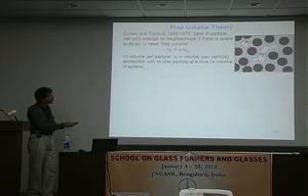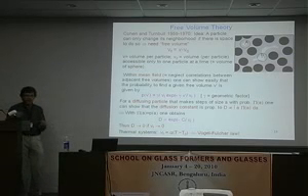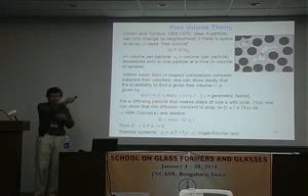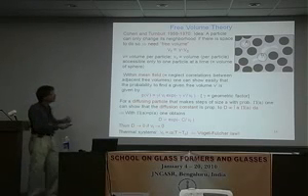And so what you introduce is the so-called free volume, which is the volume which is accessible to the particle. That is to say, the white volume here. It's the sum over all the white volumes divided by the number of particles in order to get an intensive quantity. So that's your V_F. Now, you are making a mean field approximation. That is to say, you are not looking whether or not these white patches are correlated geometrically. You say every particle has the same amount of free volume accessible.